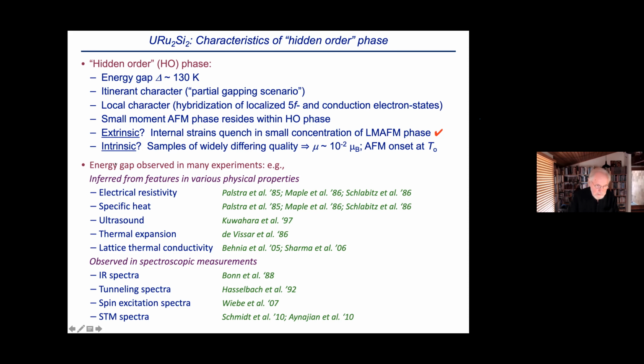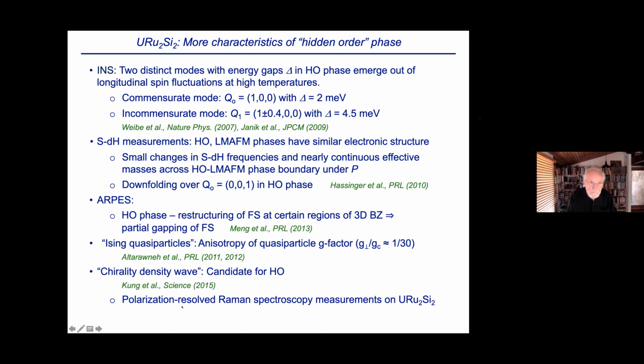also early measurements show that there's an energy gap where it's been observed in all these experiments we mentioned here, and also in various spectroscopic measurements: infrared, tunneling, spin excitation spectra from inelastic neutron scattering, and STM and so on. Okay, so a little bit more. From inelastic neutron scattering, there are basically two distinct modes with energy gaps in the hidden order phase that emerge out of longitudinal spin fluctuations at high temperatures. One of them is a commensurate mode with this wave vector and a gap of about 2 millielectron volts. And then there's an incommensurate mode, Q1, with an energy gap of about 4.5 millielectron volts.